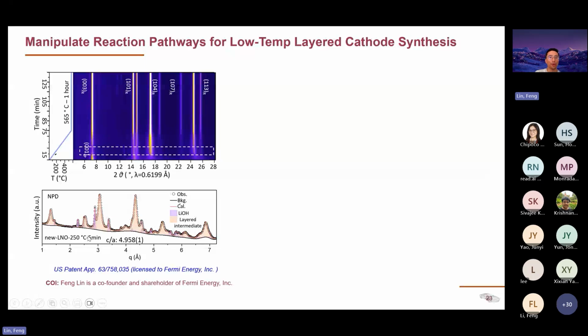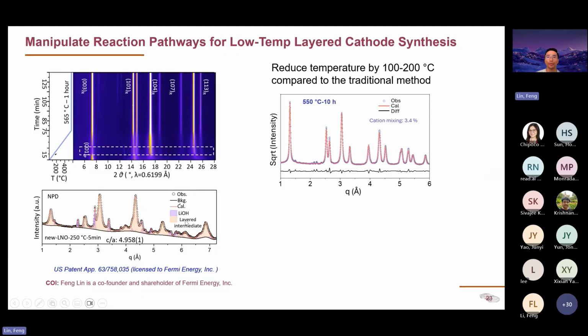We start to see buildup of the layer phase. And the C to A ratio is 4.958. That's very close to a nice layer phase. So this is called layer intermediate phase. If you look into the final calcination at 550 C for 10 hours, now you get a very beautiful layer phase, which is a 100 to 200 degrees C temperature decrease compared to the traditional process. And the cation mixing is only 3.4%.